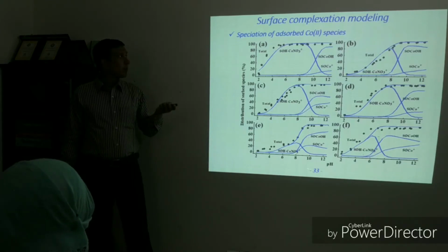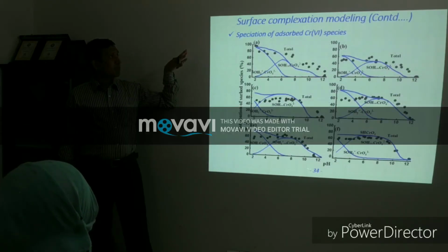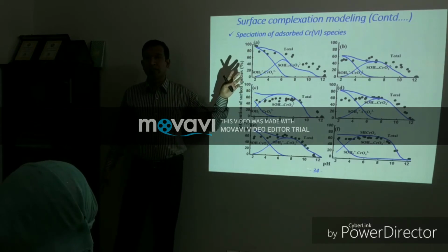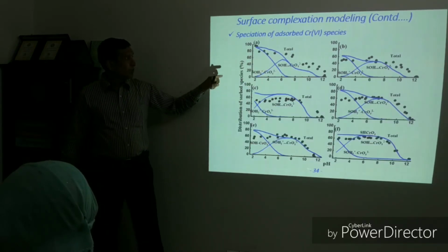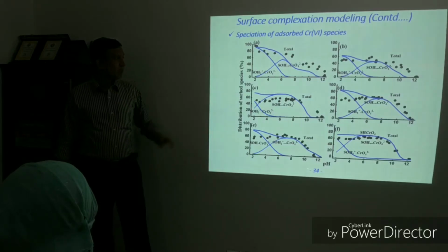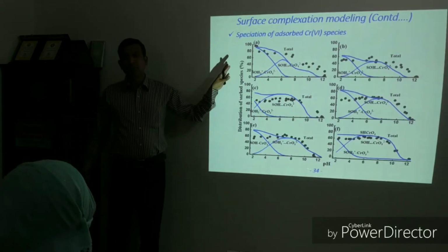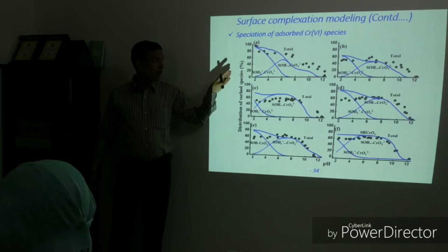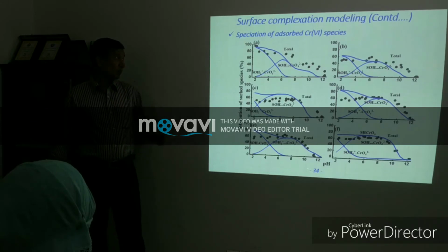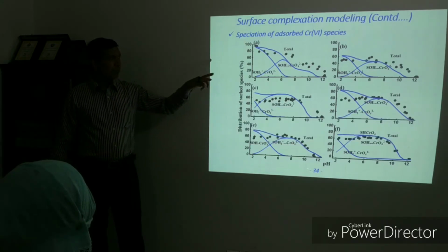Then we have studied speciation of chromium species, considering one inner sphere complexation and one outer sphere complexation. So from this study, we see that inner sphere complexation formed at low pH and outer sphere complexation occurred at higher pH due to mutual repulsion between the negatively charged surface and anionic chromium species.